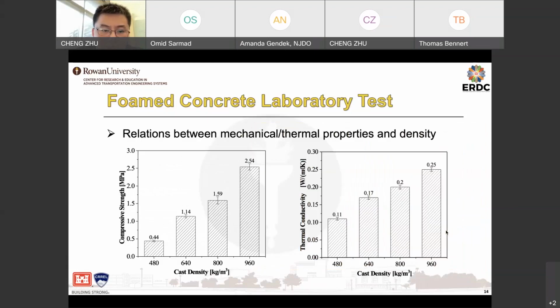The results show that with increasing foam concrete density, the compressive strength increases. That is because of the reduced air bubbles in the concrete sample. And with a higher density, the thermal conductivity values also increase.